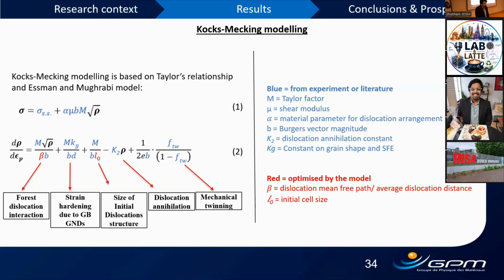Yes, certainly it is possible. It will be interesting. In fact, here at JPM, engineer Renaud Henry works on micromechanical testing. So it will be interesting if we could compare this micromechanical testing of LPBF samples with the model and try to validate it. I think the differences which might occur in this comparison are probably size effects, because if we consider only one cellular structure or two cellular structures, then whether we have a grain boundary in the middle or not might induce some more questions. But certainly it would be interesting to validate the model.